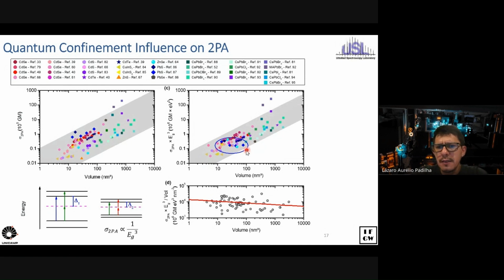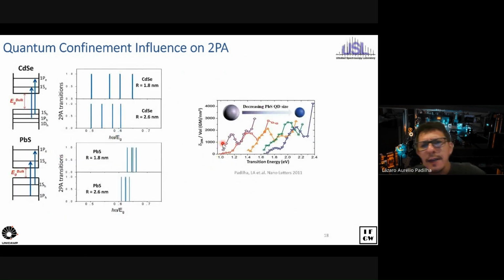Or it means that apparently it becomes smaller as the quantum dot becomes bigger. And in fact, if you look at this, for cadmium selenide, for example, when you reduce the size from 2.6 to 1.8 nanometer, your two-photon allowed transitions spread around the energies, making a very drastic reduction on the density of states. What's not so true for lead sulfide?